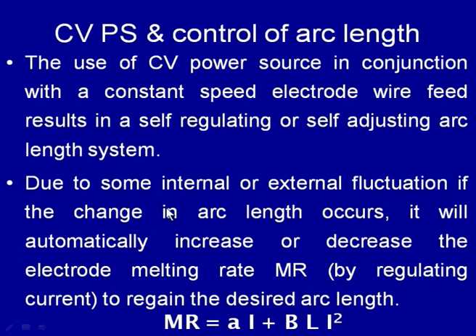So, under these conditions, when due to a fluctuation caused by any reason the arc length changes, this change in arc length changes the arc voltage, and the change in arc voltage associated with the constant voltage power source regulates the current significantly, and a significant increase in the welding current causes a change in the melting rate. Under the conditions of constant feeding of the electrode wire, if the melting rate is regulated, then this combination helps to obtain the self regulating arc or the constant arc length.